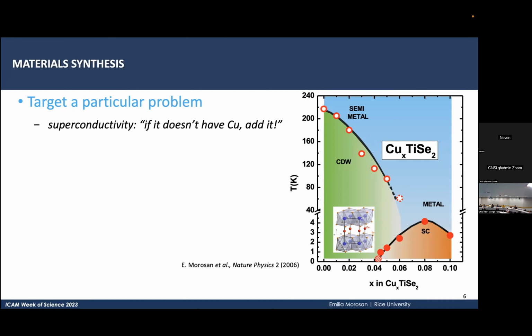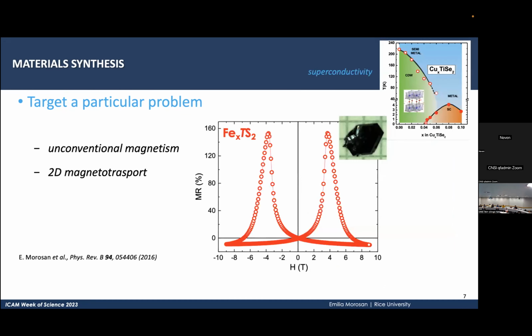But if I'm honest, I will tell you that we planned to look for spin 1/2 magnets. That's why we're using copper in a lot of the dichalcogenides. So at the time, I put copper and then iron and other things in a lot of dichalcogenides just to see what comes out. And what came out was this great result of superconductivity in copper intercalated TiSe2. In the same vein, I intercalated iron in various compounds, and no, it wasn't because I knew that I would get this unconventional magnetism or really large magnetic transport.